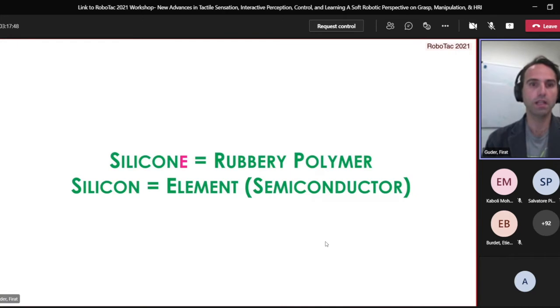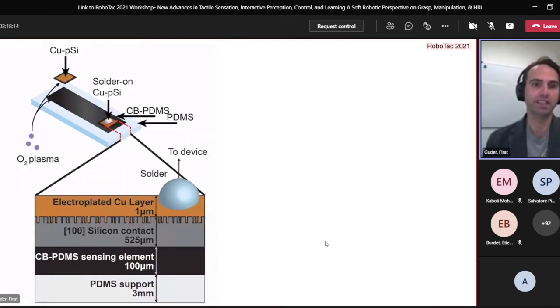For those of you that are not too familiar, I will use two terms that are very similar and often mixed. Silicones are the rubbery polymers, and silicon is the element that's the semiconductor used for making chips and so on. These two terms are quite important, especially in this study. So the way our contact works is that it's silicon. We take a silicon wafer, and then we create a nanostructured surface on one side, which we can then use for electroplating copper. Because copper is very easy to solder, we can then bond the other side of the silicon piece onto the silicone layer, and the copper side can just be soldered onto an electrical wire.